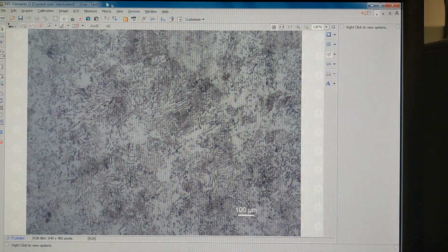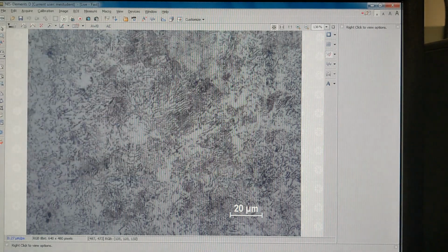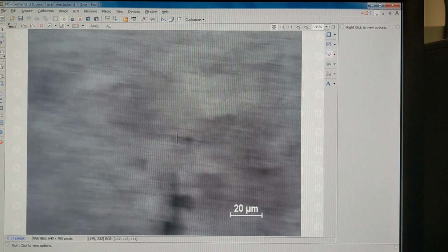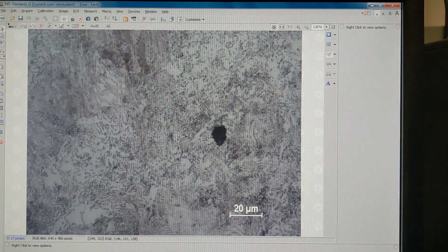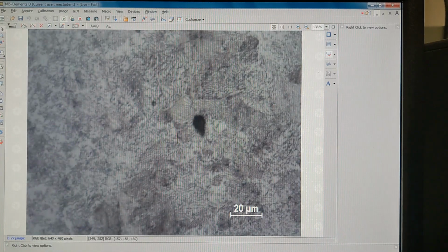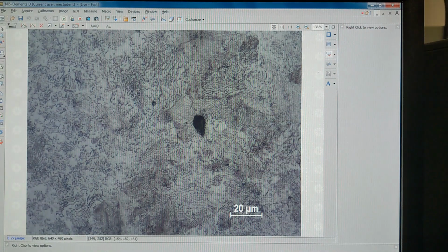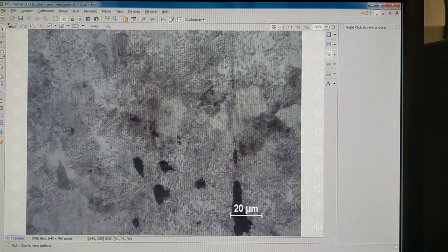And let's fix our scale bar, because right now we are at 50 times. If you fix our scale bar, you see we're at 20 microns. So here is our sample. As you can see, it's pretty uniform. See, there's a big porosity, a void right there. Here's another one. You can tell it's a void often because you can focus into it. You can actually focus on the bottom of the hole. But we see this is a lot of pearlite and some ferrite in the mix here. So this is with 0.18% carbon, we remember.